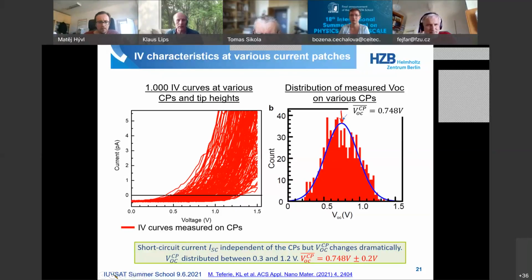And what we find experimentally, if we put a connecting contact on the solar cell that then collects on a large area, let's say 2 or 4 square centimeters, it comes out at 0.74 volts. So it seems that the average local voltage is identical to the voltage that we measure by summing up all the various IV curves, but you can have hotspots where the open circuit voltage is much higher than what you would expect. And that means that we have local potentials, and we found out also where these come from, but I don't want to talk about that because that's another talk for itself.